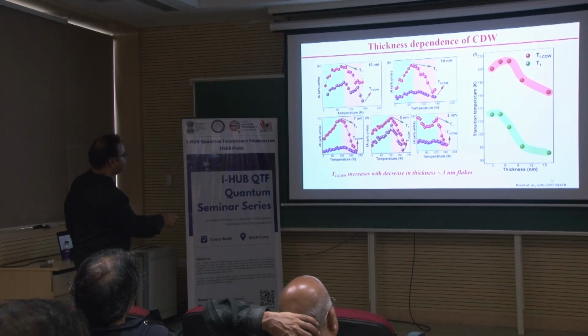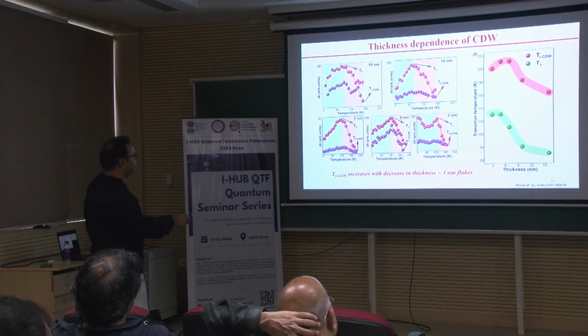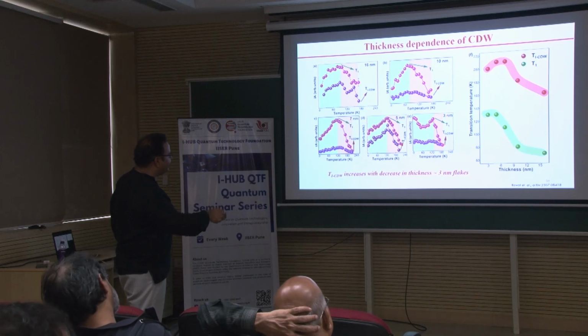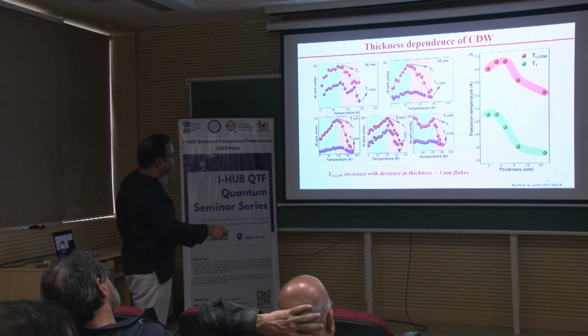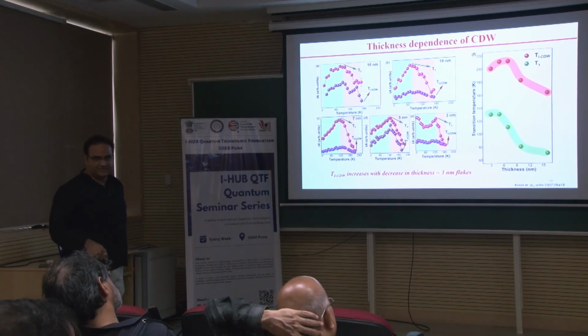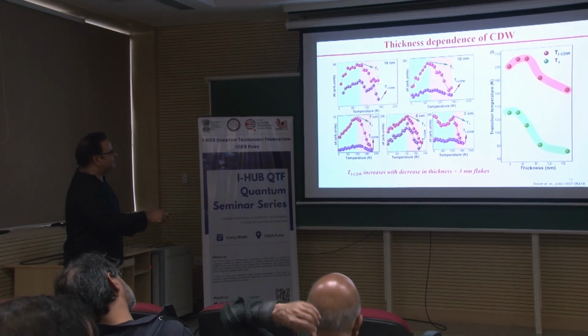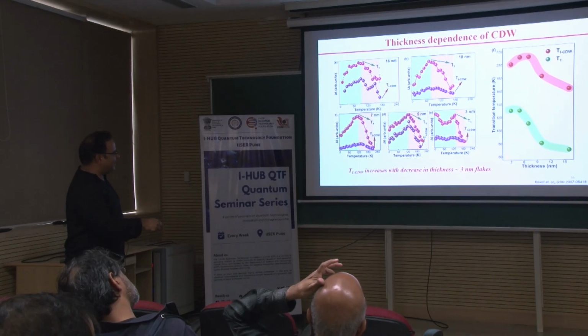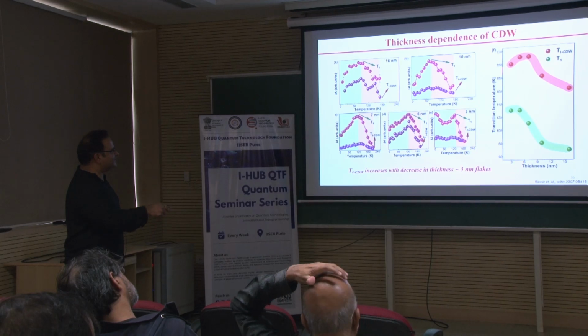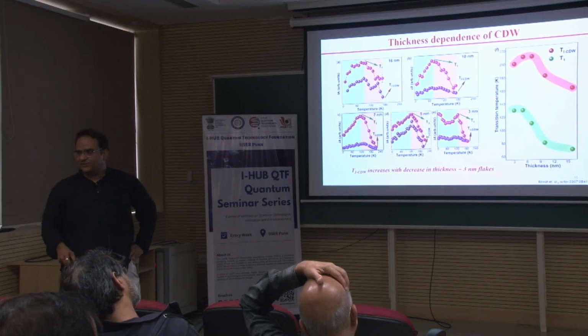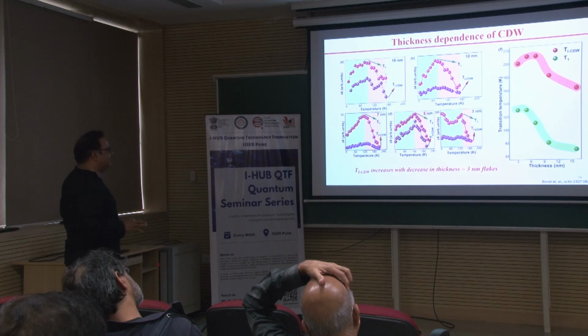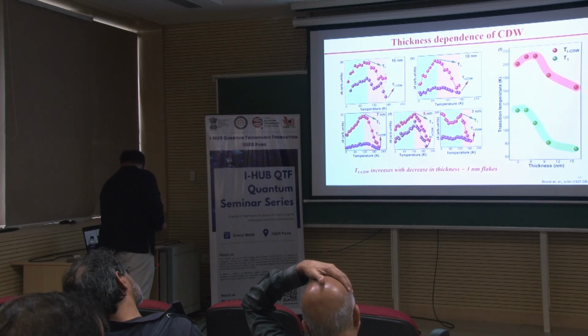This is TICDW, the incommensurate charge density wave, 5 nanometer, 3 nanometer, and this is the thickness versus transition temperature. So, charge density wave instabilities at lower thickness can exist at higher temperature. Very interesting actually. And these are the signature of the charge density wave materials.